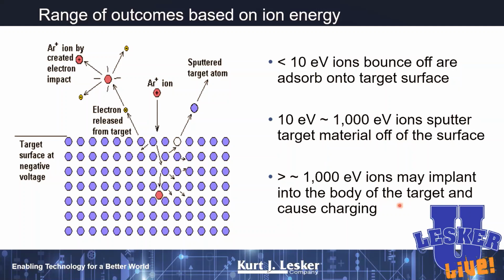If it's more than 1,000 eV, there's a possibility that that argon ion is going to penetrate and embed itself into the body of the target. And if it does that, it's going to start to charge the target. If the target itself is an electrical conductor, like a metal, that's not going to be an issue. We can shunt that charge away. If it's a ceramic, then we have an issue, and we'll talk more about that in a while. But as an artifact of ionizing the argon, we're going to create some secondary electrons, and those are going to be trapped by that magnetic field at the surface of our target. They're going to continue to rotate around that surface and help us create more argon ions.